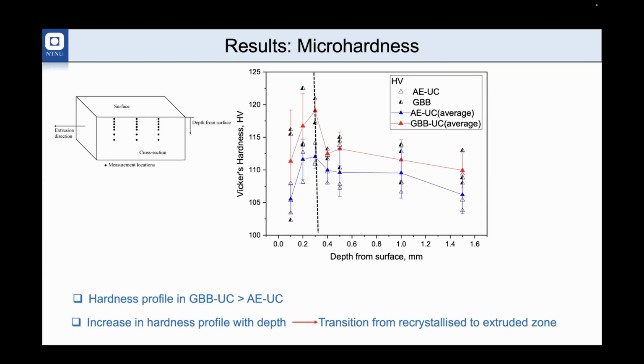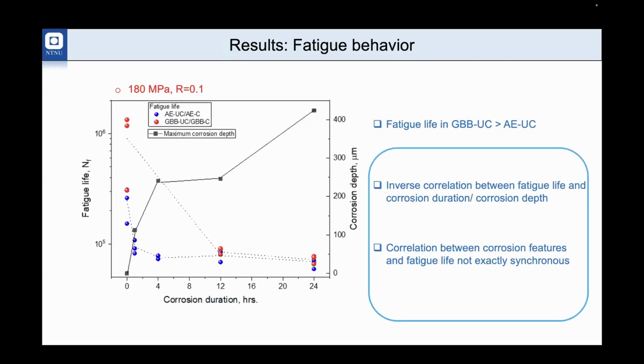We also did some microhardness characterization on the material, and you can see that the microhardness shows an increasing trend followed by a decrease, which marks the transition from the recrystallized to the extruded zone. And for the glass bead blasted, the microhardness is obviously higher compared to the controlled condition. The reason is that glass bead blasting induces some compressive residual stress and also work hardening. So obviously it would increase the microhardness.